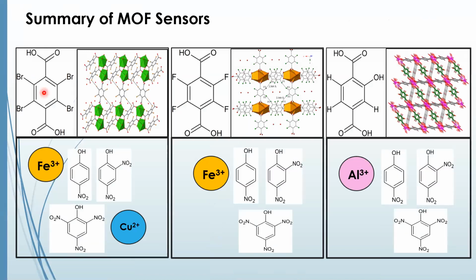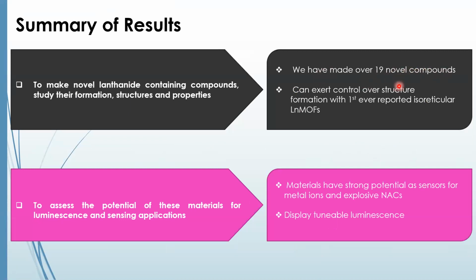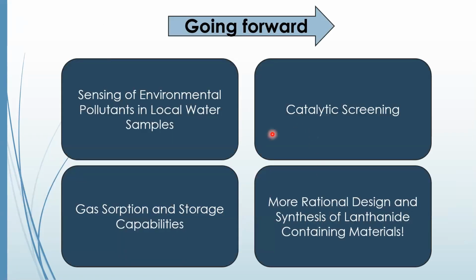So in summary, we have synthesized and structurally characterized quite a number of polynuclear compounds of lanthanides, as well as framework materials. The tetrabromo and tetrafluoro, the tetrahalo compounds we have shown are good sensitizers for metal ions and explosive nitroaromatics. And we have shown, in fact, that the terephthalates, the hydroxyterephthalate compounds, MOFs, are also sensors for aluminum. And so I say, in summary, we have made over 19 novel compounds, and we have exerted control over the formation, and we reported the first ever isoreticular lanthanide MOFs. The materials have strong potential as sensors for metal ions and explosives, and they display tunable luminescence. And going forward, of course, we want to look at catalytic activity, gas absorption, and sensing of local pollutants.